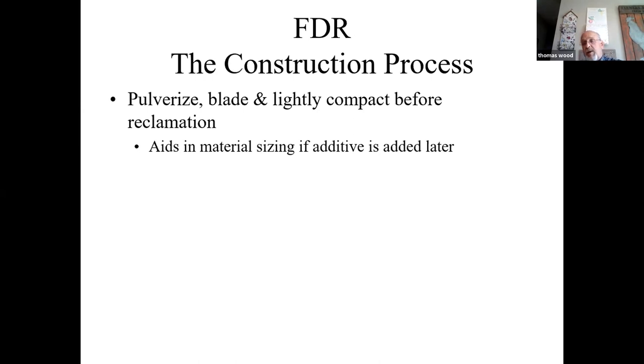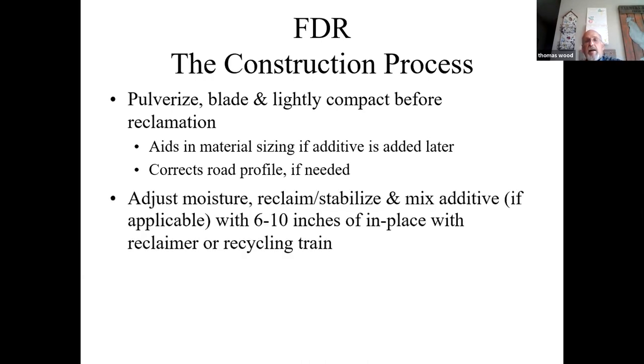And back to that question, if you have a lot of chunks and they're not meeting the 3-inch minus, I believe MnDOT spec is 3-inch minus, make them either slow down or make them regrind it until they do meet it. It allows you, after you pre-shape, and I'm talking about stabilized FDR, to correct the profile if needed, and you can adjust the moisture, reclaim, and mix additives as applicable to 6 to 10 inches in place with a reclaimer.